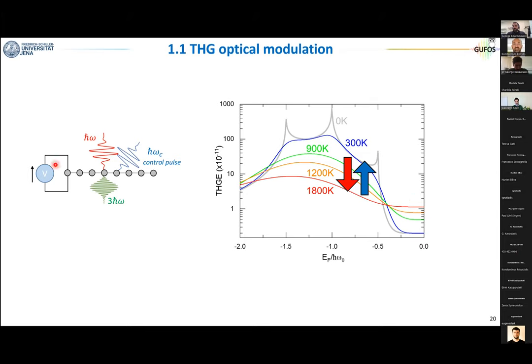We can now fix a certain Fermi energy with the gate voltage. Then we add another pulse that we call the pump or the control pulse. And with this one, we only change the temperature. So the pump pulse will be absorbed, we will change the temperature of the sample, and the temperature will affect the efficiency of the third harmonic.